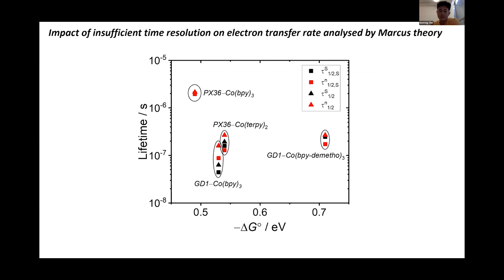So what would be the impact of this insufficient time resolution when we study the structural effect using Marcus theory? For example, if you have the lifetime plotted as a function of delta G, in one circle there are four different plots, but they all have the same sample. For example, this one was measured using the faster setup with fitting, but the other one is measured using the slow setup and just determined by the graph. So it has a fairly significant difference.